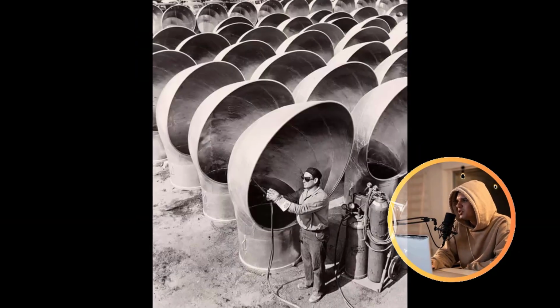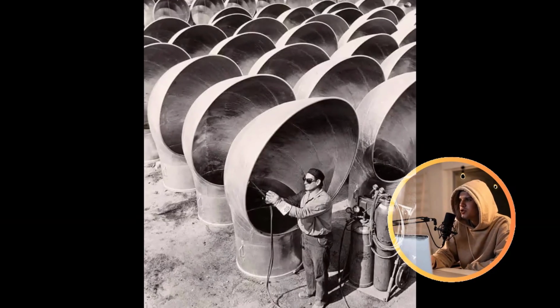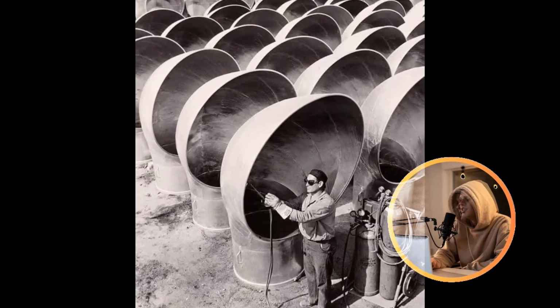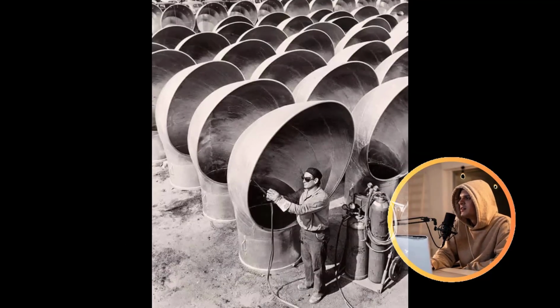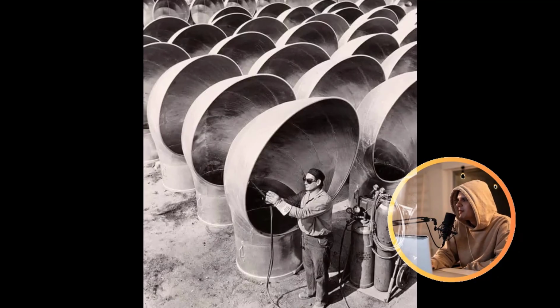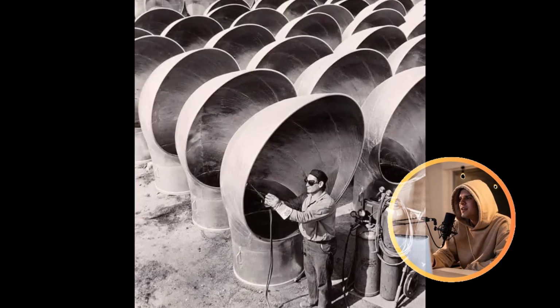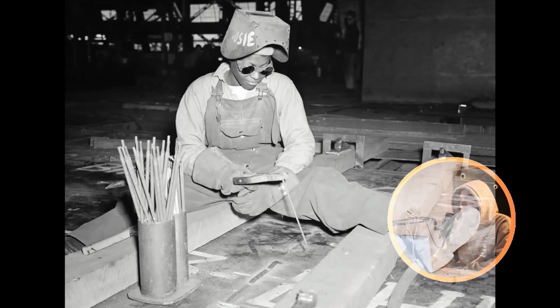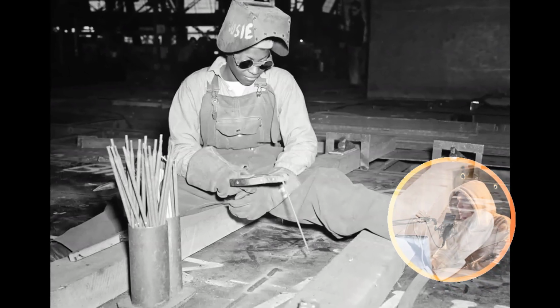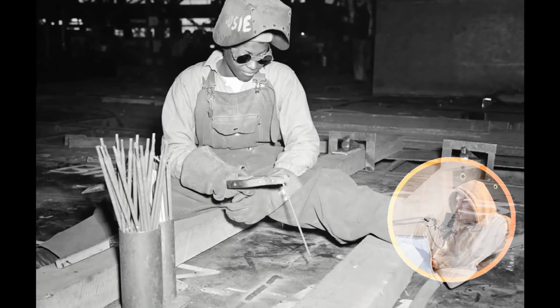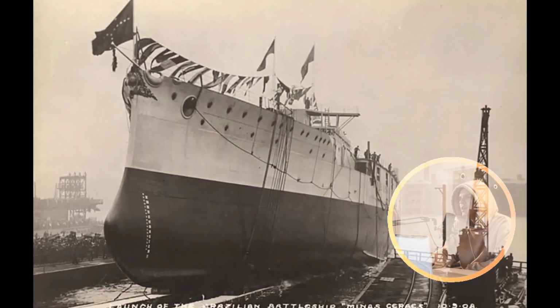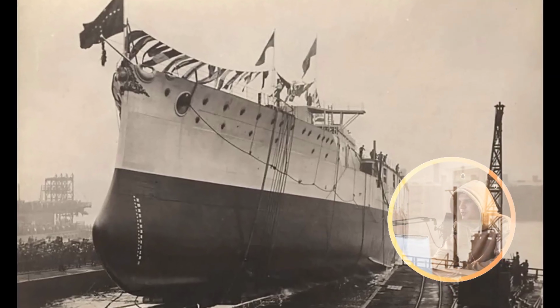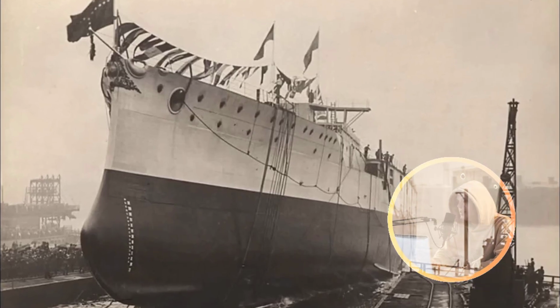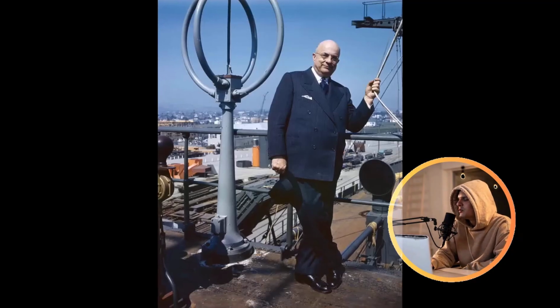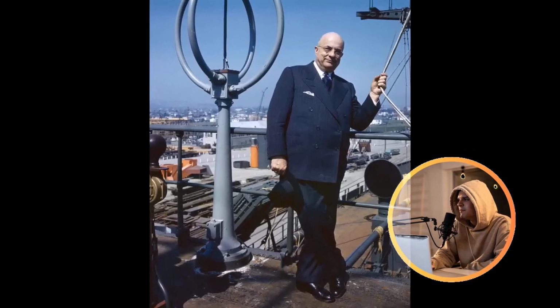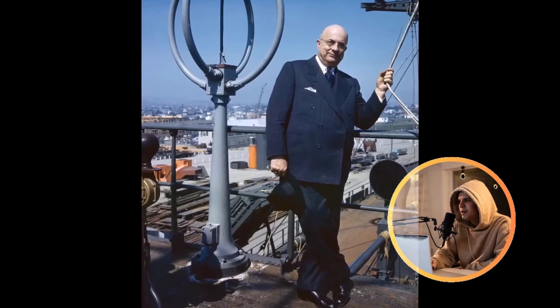Regrettably, no one at the time had adequately considered that sharp internal corners act as potent stress concentrators, capable of multiplying applied loads by enormous factors. Each wave that caused the hull to flex and strain sent acute stress spikes through these vulnerable corners. When these localized stress intensifications were combined with the residual stresses locked in by the welding process and the brittle nature of the steel at low temperatures, these corners transformed into prime crack initiation sites, lying in wait for the precise confluence of conditions to trigger a catastrophic structural collapse.